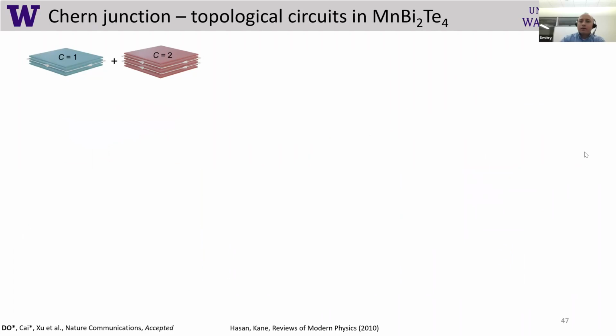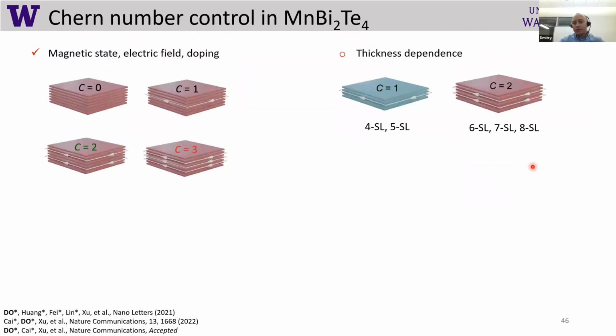Yeah, so your question is about the Chern number dependence. As I said, we see Chern number 1 in all flakes from 4 layers to 8 layers. So Chern number 1 can always be there. We see Chern number 2 only in 6, 7, and 8 layers. Other people see it otherwise. I'm not sure why. In our case, we measure thickness not only with AFM, we also determine thickness with RMCD. When we do magnetic state dependence, we can see if the layer number is even or odd, depending on the critical field of the transition from AFM to canted AFM. So we have AFM measurements and RMCD to confirm our thicknesses. I don't know about other people, but that's what we did.